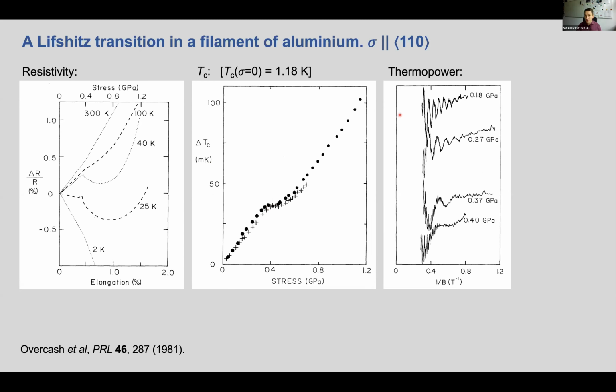In the thermopower, they can see clear quantum oscillations. So at 0.18 GPa, that is about here, about 0.2% elongation, they see a relatively fast oscillation frequency. At 0.27 GPa, this is slowed down. At 0.37 GPa, we're looking at this larger oscillation here. That frequency has got smaller, and at 0.4 GPa, it is extremely small.